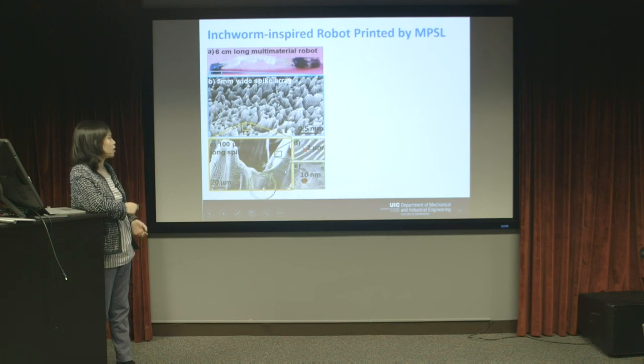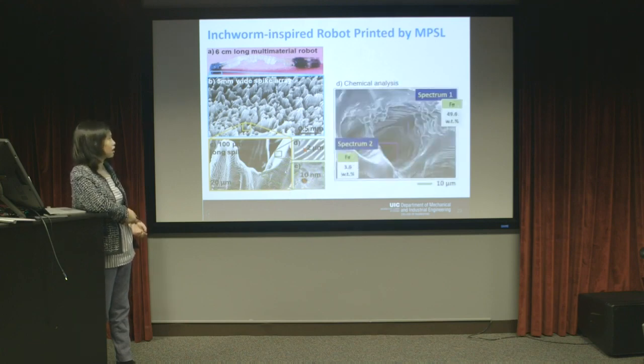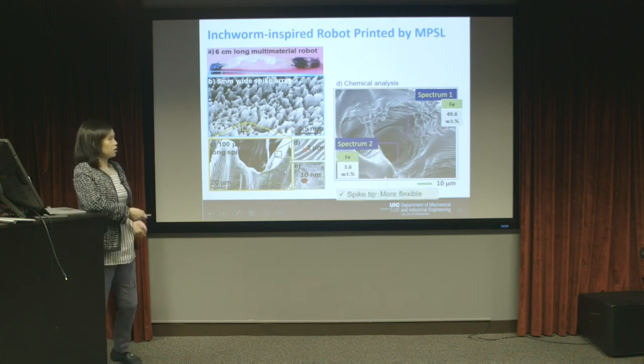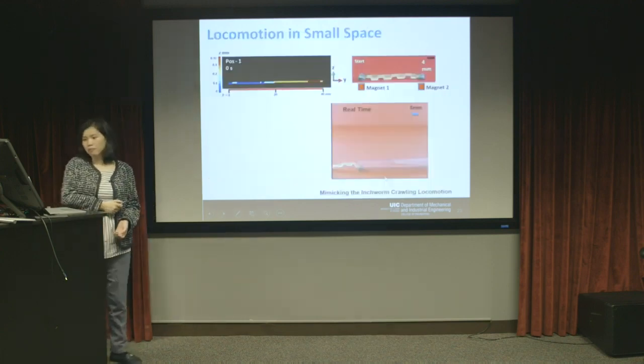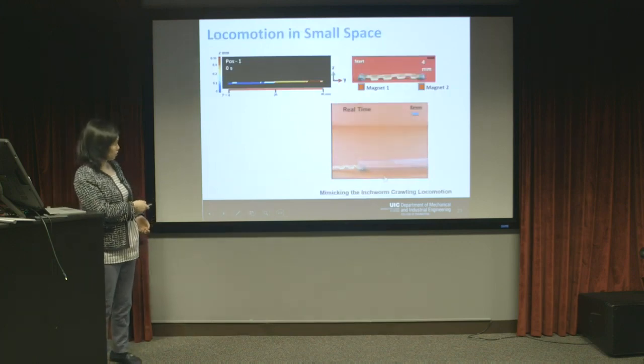If you look at the bottom more carefully, you'll see that it contains nanometer holes. With those features, we also analyzed the chemical composition. You can see that spectrum 1, which is the bottom of the spike, contains more iron, because we have more iron oxide particles. And the tip has fewer iron oxide particles, so that the tip can be softer. Okay, so let me show you some figures.